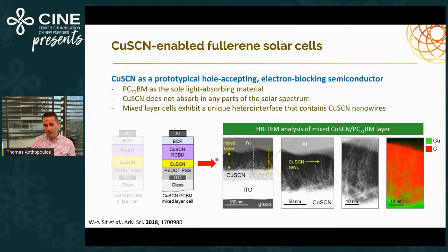So when we analyzed our devices, we saw this spontaneous formation of mesostructure-type nanowires of copper thiocyanate embedded within the dark areas, which is the actual fullerene. And as a result, we had a very nice interpenetrating network of a P-type material accepting the holes, but does not really donate any electrons. And all the photoexcitation, the charge generation, is happening within the actual fullerene. So it was, to my knowledge, one of the, or maybe the, highest efficiency fullerene-only based solar cells. But that demonstrated the power of copper thiocyanate.